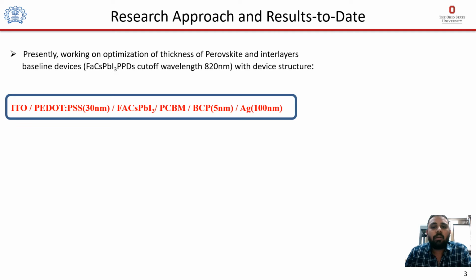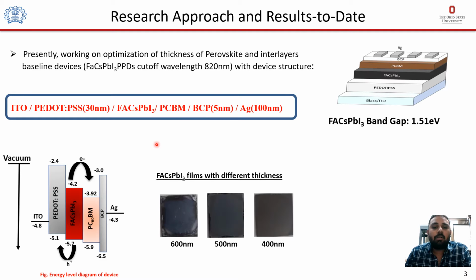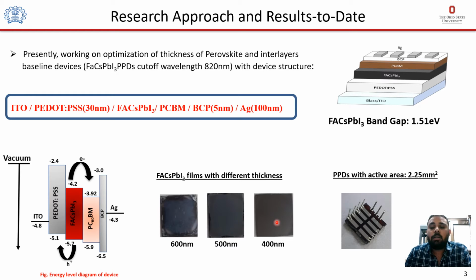So currently we are working on this device structure which has a cutoff wavelength at 820 nanometer, where ITO and silver are the bottom and top electrode respectively. PEDOT:PSS, PCBM and BCP are various interlayers. These are the different thicknesses that we are currently working on: 600, 500 and 400 nanometer, and this is the image of our final device with an active area of 2.25 mm square.